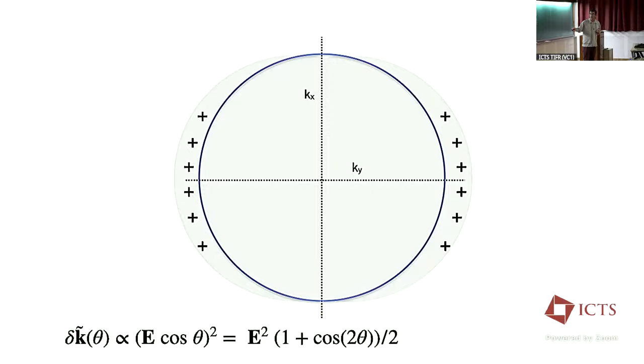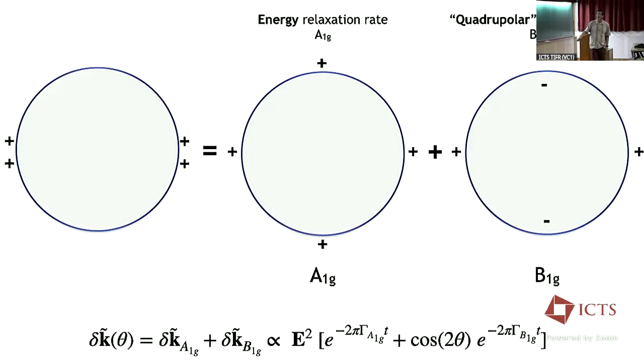And of course, I can decompose it like this, and there's an S-wave part and a D-wave part. The S-wave part is associated with exciting everywhere around the Fermi surface, and the D-wave part is associated with, let's say, exciting it here and exciting it there, but de-exciting it here and there. And I've represented that graphically here. Again, you could imagine taking the Fermi surface and exciting it here and there, and I can write that as a superposition of this one, which is an A1g deformation, where I've gone around and excited everywhere around the Fermi surface, superimposed with this one, which we would call the B1g. By this, I want you to just add up plus signs and minus signs, and you'll see that you can take that plus that and get that.